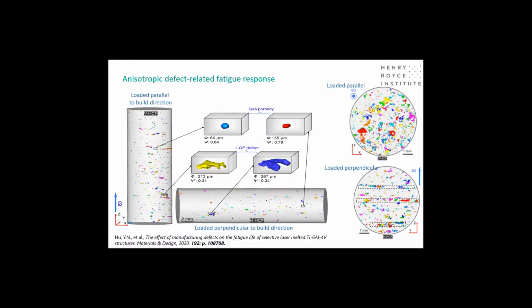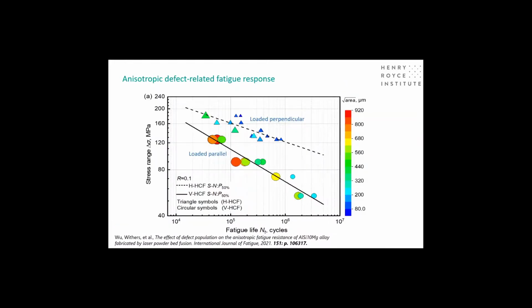And when we look at the defect distribution, you can see that the defects when loaded parallel to the build direction, because they're pancake shaped, present a very large cross-sectional area, whereas when you look at the ones loaded perpendicular to the build direction, the pancakes are sideways on, and because the pancakes are sideways on, they present a smaller crack area, so they're less likely to lead to fatigue failure. And that's reflected in the SN curve. So you can see here that the SN curve for samples tested loaded perpendicular to the build direction shows a higher fatigue resistance than those tested parallel to the build direction.